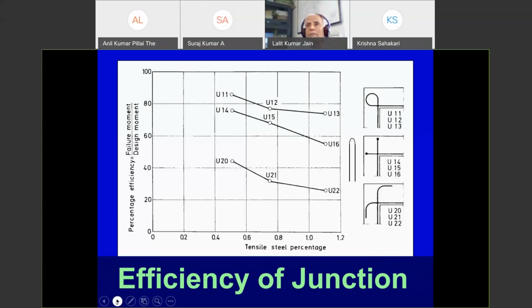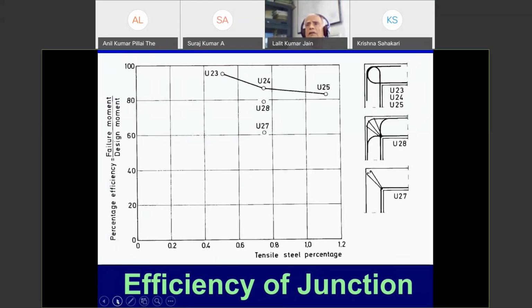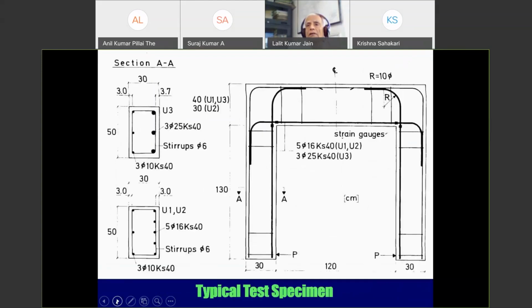Now they have found that instead of doing all this, the efficiency doesn't go up. The best thing is to take the bar and bend it back as a hairpin into the same member. That gives the highest efficiency, but not even 100%. And looking at the crack width, they realized that to control crack width, we have to have an additional bar. Now this was the test program. This bar is anchored here, this bar is anchored here. On the other face, the compression side, we provide nominal anchor bars, much smaller bars.